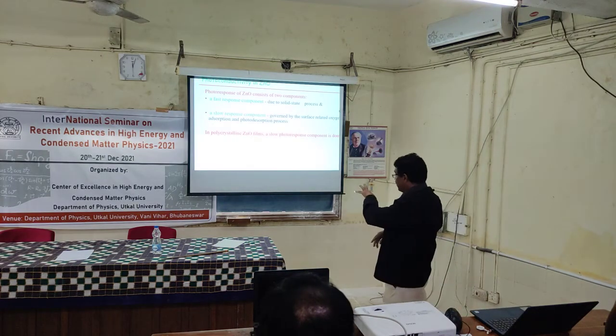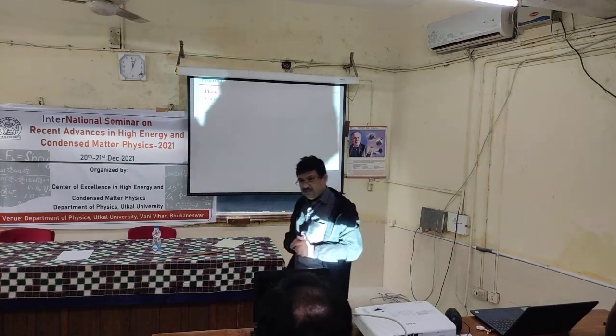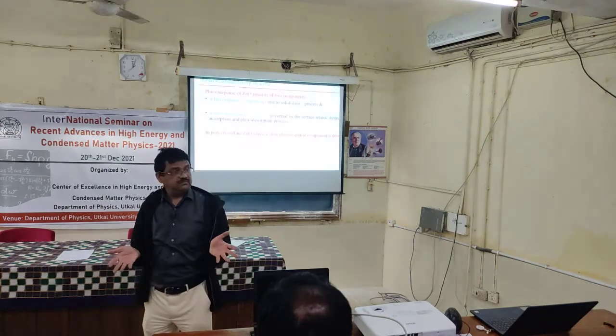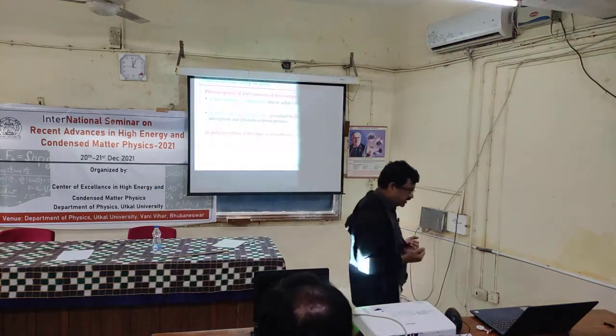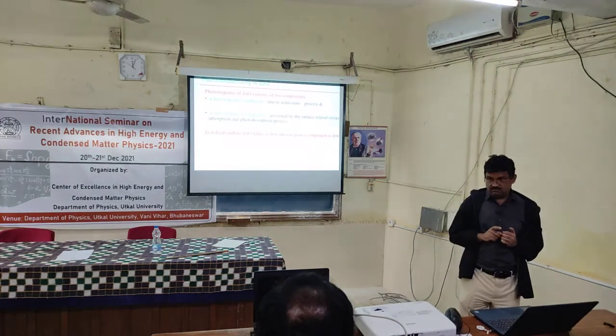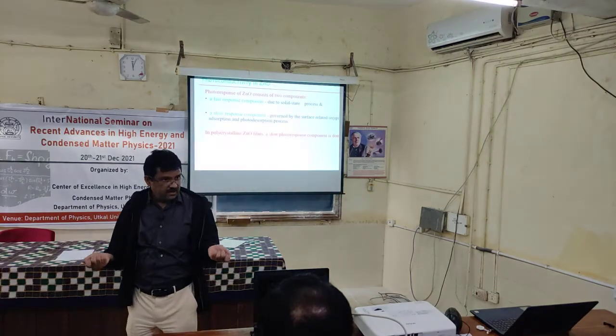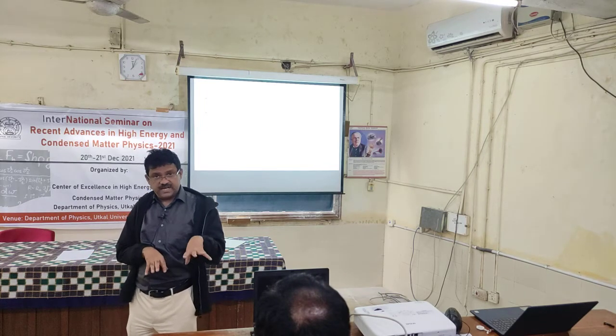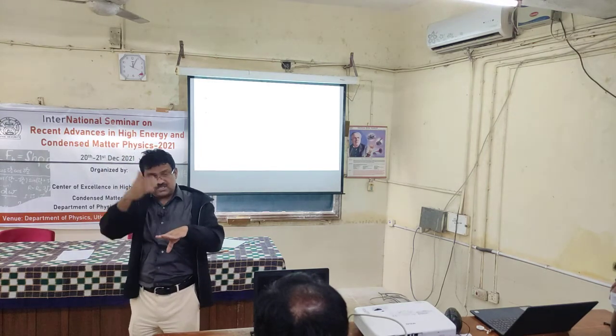Another problem associated with zinc oxide is that if it is exposed to ambience, it has the affinity to attract oxygen, which is a slow process. For a simple semiconductor, if I shine light, I should immediately generate the electron hole pair, and when I turn it off, the photocurrent should immediately go to zero. But what happens in zinc oxide? There is oxygen adsorption, and because of the electronegativity of oxygen, it has the tendency to take electrons from zinc oxide. The adsorption of oxygen is a slow process, so you see the current drops slowly. The response time is very slow in zinc oxide.